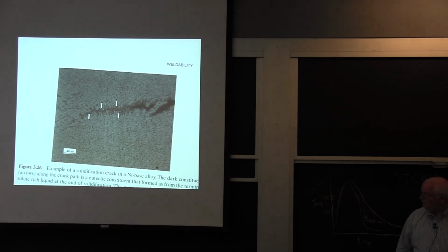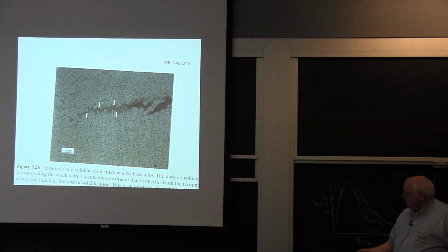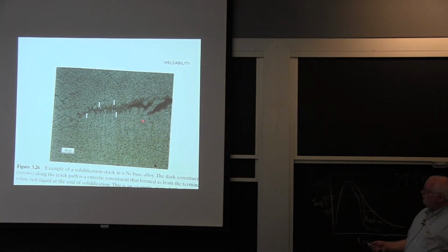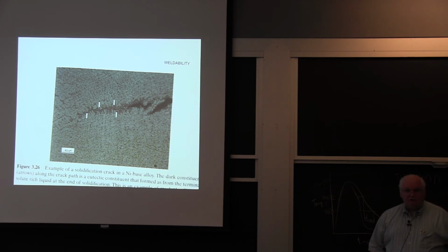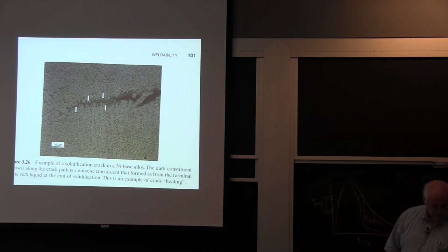And if you want to see what it looks like, here's a picture of the microstructure of a nickel-based alloy. They call it solidification crack, but this is the base metal structure, and it partially melted along some grain boundaries, and some of the liquid in between these grain boundaries migrated, and they call this a self-healing crack. Well, this might be self-healing here, but these two weren't self-healing. They're still voids, okay? So it's not a great situation.